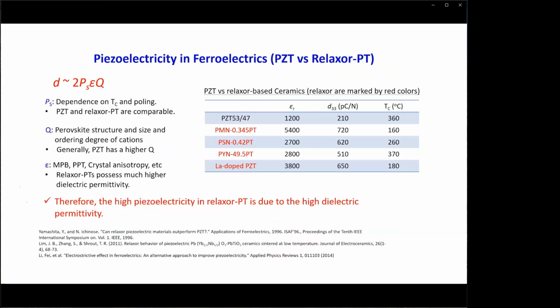For perovskite piezoelectrics, the piezoelectric coefficient is actually related to spontaneous polarization PS, electrostrictive coefficient Q, and dielectric permittivity epsilon, as shown in this equation. Now, let's make a comparison of Relaxor piezoelectrics and PZT ceramics. Generally, the spontaneous polarization PS is dependent on the Curie temperature, so Relaxor-PT may not have a higher PS when compared to PZT. The electrostrictive coefficient Q is highly associated with perovskite structure and cation ordering. Generally, PZT has a much higher Q coefficient when compared to Relaxor-PT. Therefore, the high piezoelectric coefficient d in Relaxor-PTs should be attributed to the high dielectric permittivity.